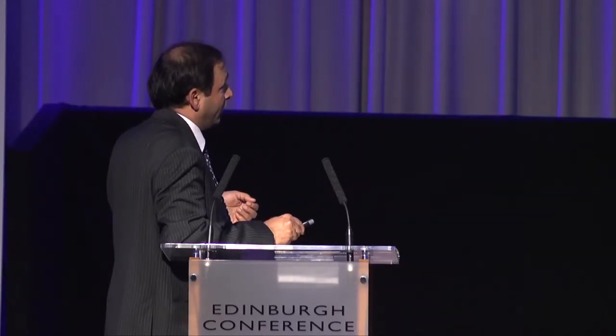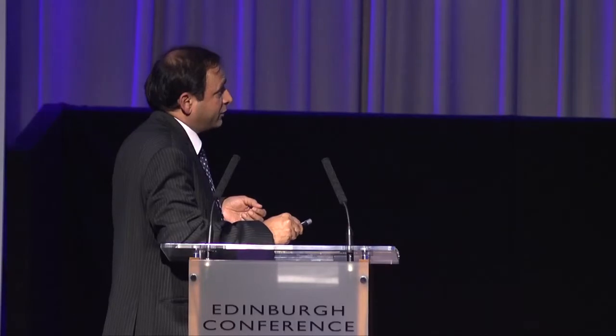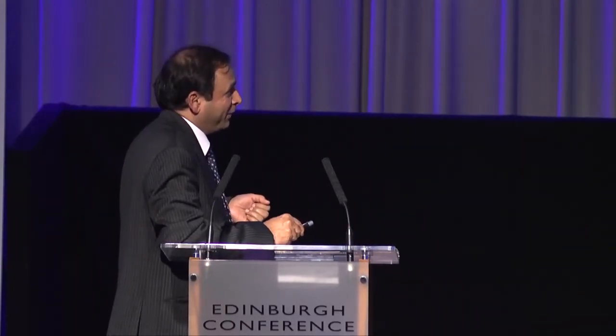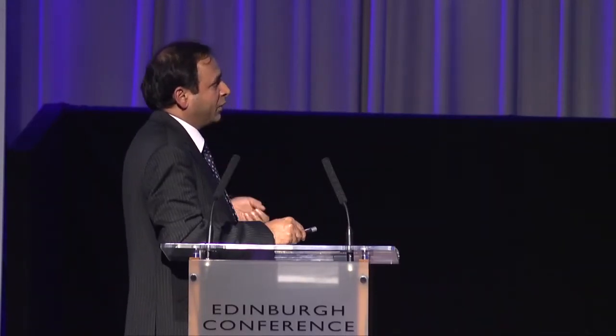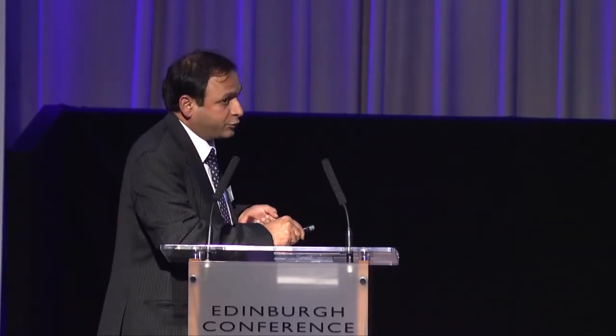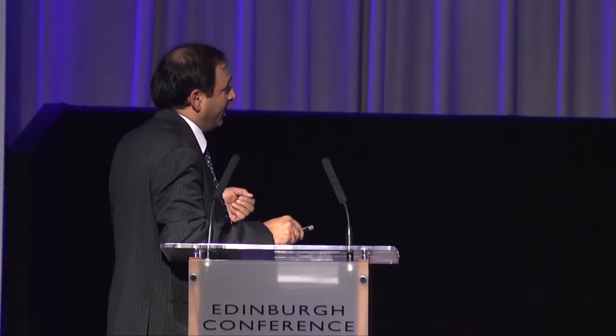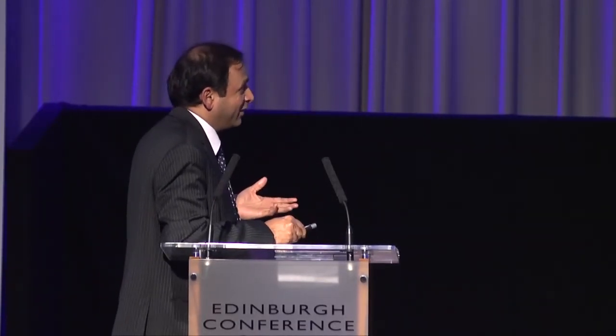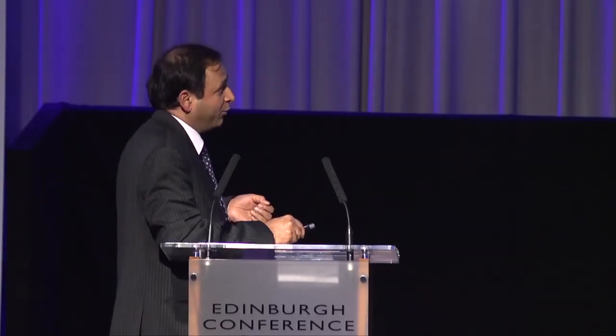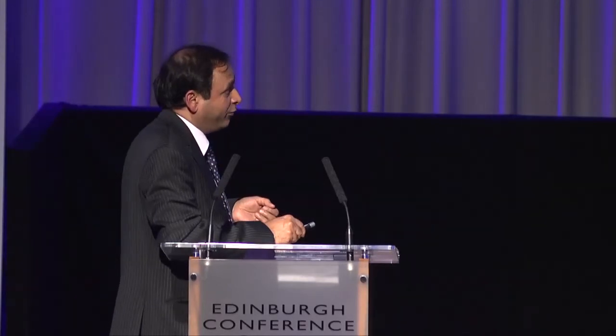Third generation ones are new developments on, say, dye-sensitized solar cells and organic photovoltaics. Some very good developments are going on in this direction. The efficiency which has been achieved here is now crossing, at the cell level, more than 10% already. And it is believed, with the amount of R&D efforts going on, that the only drawback in these technologies is the longevity of the devices, which is again being given due attention. We're hoping that with 10% efficiencies and 10 years of lifespan, if these technologies can really get there, they can have a very good impact on the solar PV market.